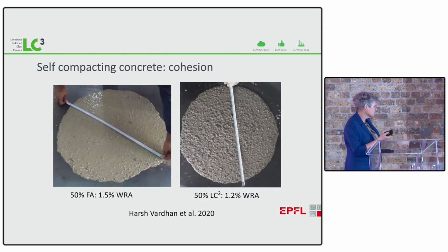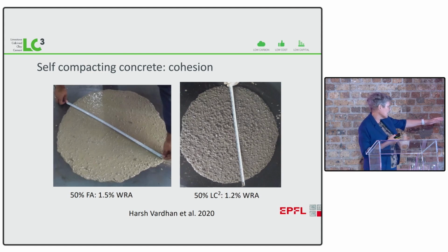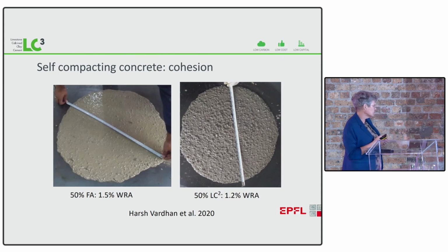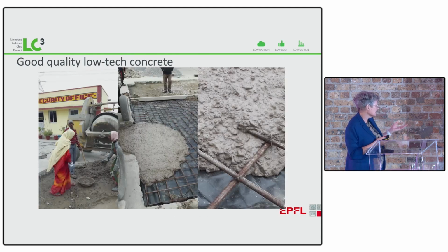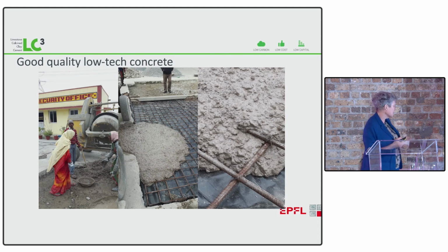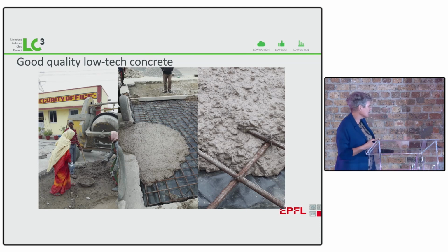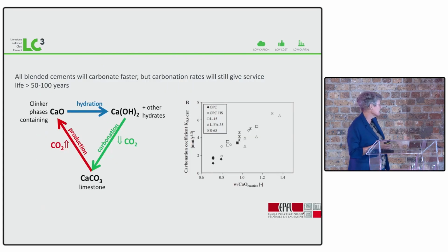This compares the admixture demand for a self-compacting concrete with fly ash and one with LC2, and you can actually see the LC2 one has a lower demand for water-reducing admixture. And this was one of the first projects we did in India. You can see that the mixing of the concrete is not at all technical. It's just done by volume batching by those people there and in a small mixer. And nevertheless, they could batch after batch obtain this very good cohesive concrete with no bleeding, no separation.